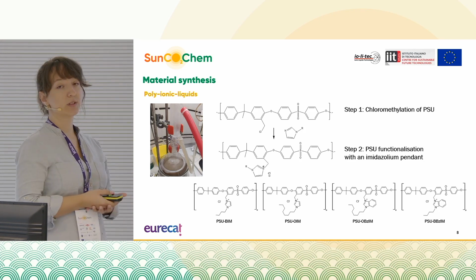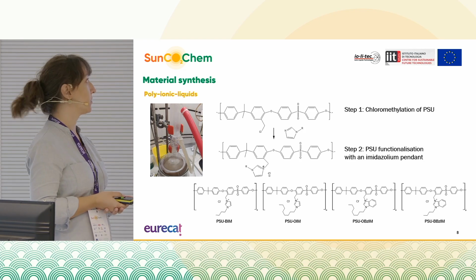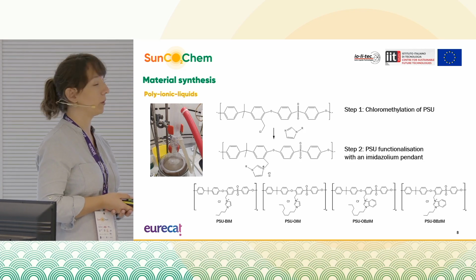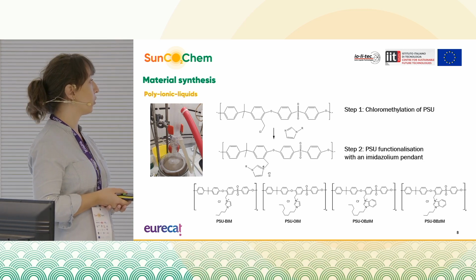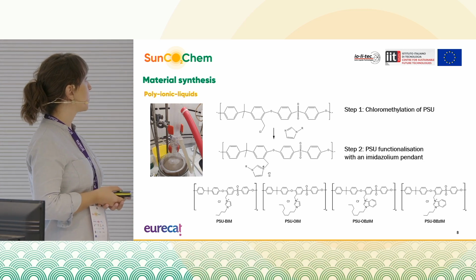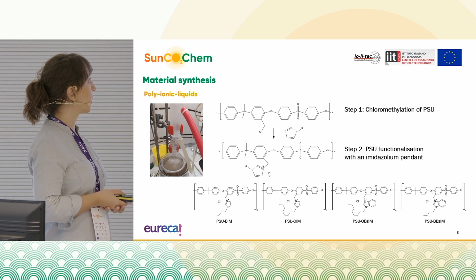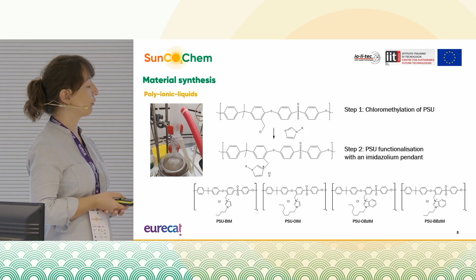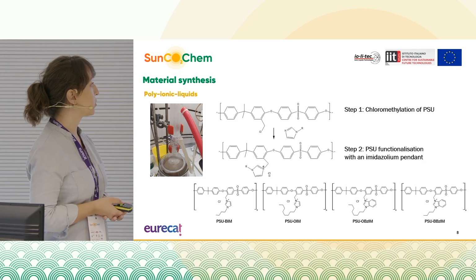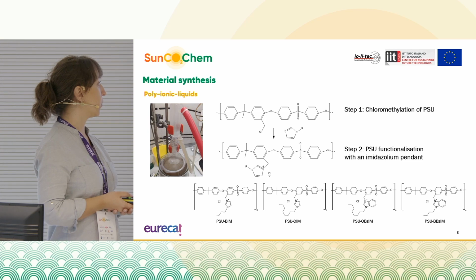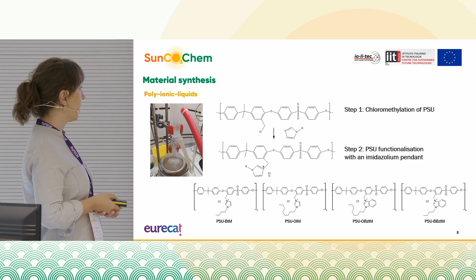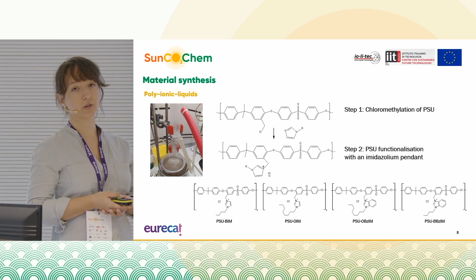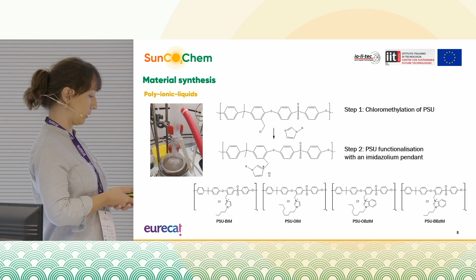The ionic liquids were incorporated in two ways. Firstly, we introduced them to the polymer through a covalent bonding. This was a two-step synthesis where we started from the chloromethylation of polysulfone, and then we passed to the functionalization with an imidazolium pendant. We chose 4 different pendants in order to obtain 4 different polymers.